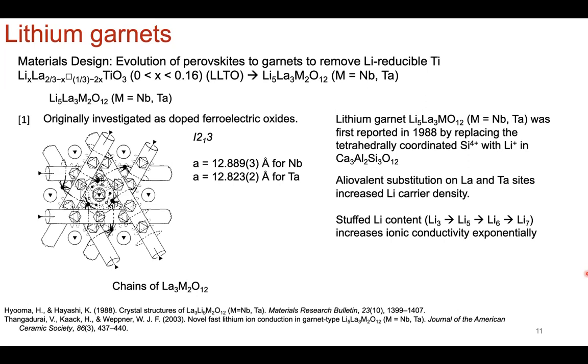So continuing on with garnet materials design. In terms of the evolution of this material, you've perhaps seen LLTO, the lithium lanthanum titanate based compounds with some concentration of vacancies that are charge balanced with the lanthanum composition. And so LLTO has evolved to this Li5La3M2O12 garnet type structure.